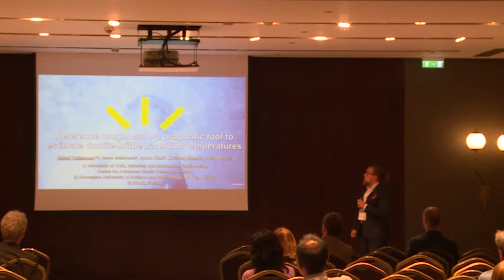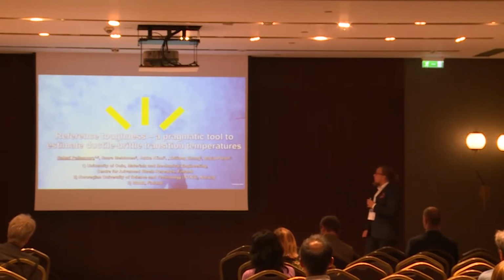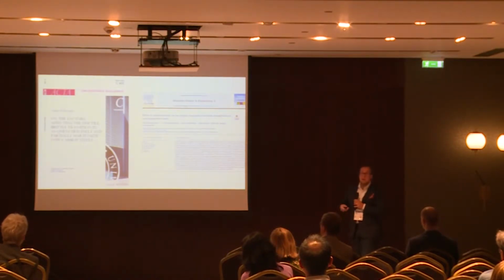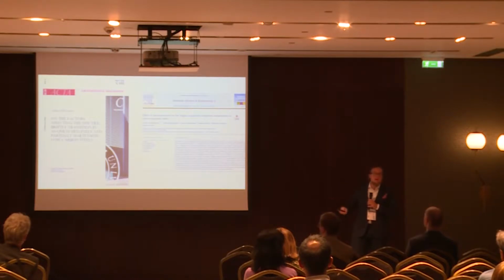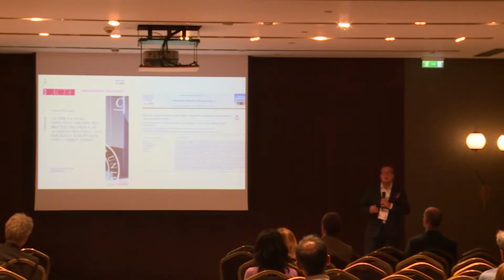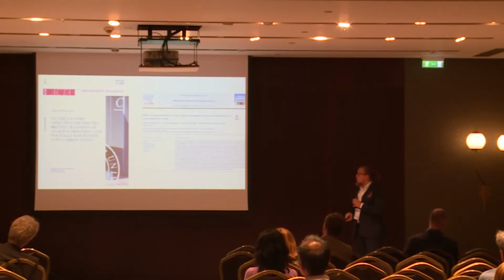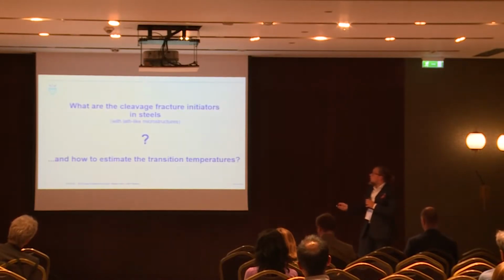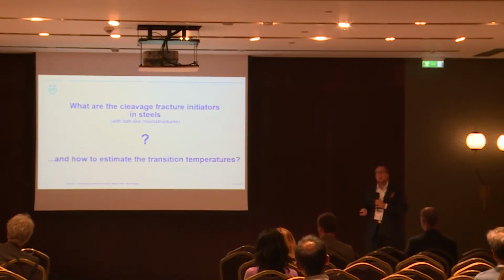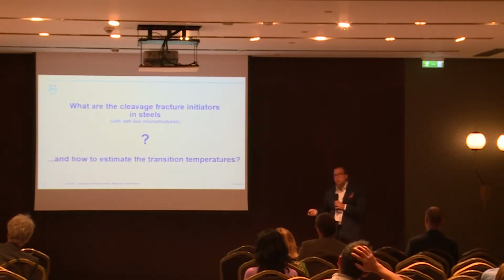So, my topic here today is the reference toughness, our concept, a pragmatic way to estimate the ductile brittle transition temperatures. This basis extends a bit from my doctoral thesis on ductile brittle transition temperature phenomena in ultra-high strength steels with lath-like microstructures, and our recent paper on the weakest links, the parameters that govern the toughness in these ultra-high strength materials made by direct quenching. So the main question is: what are the cleavage fracture initiators in steels with lath-like microstructures, and more importantly, how to estimate the toughness transition temperatures by using this knowledge.